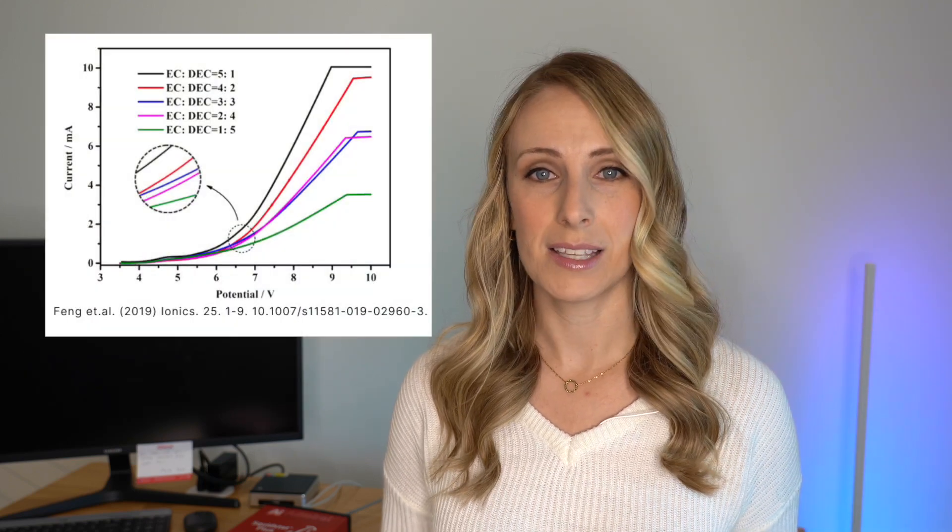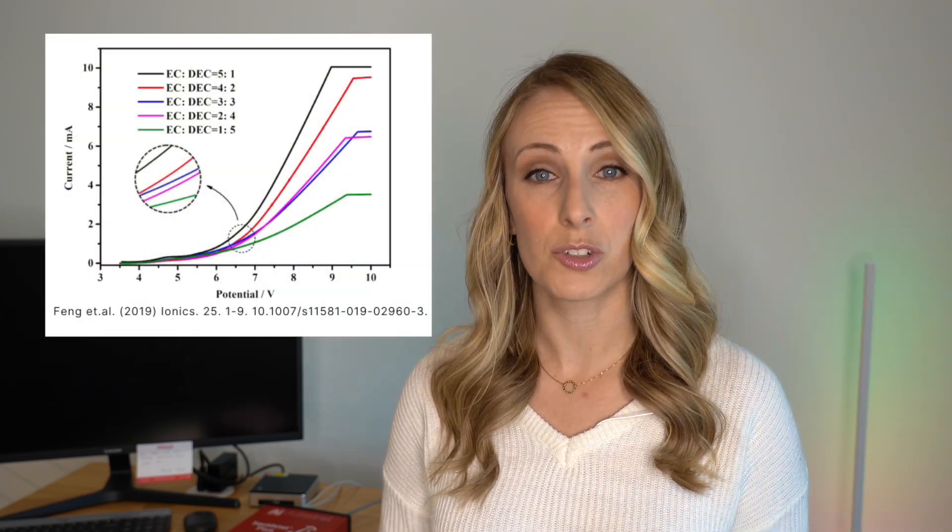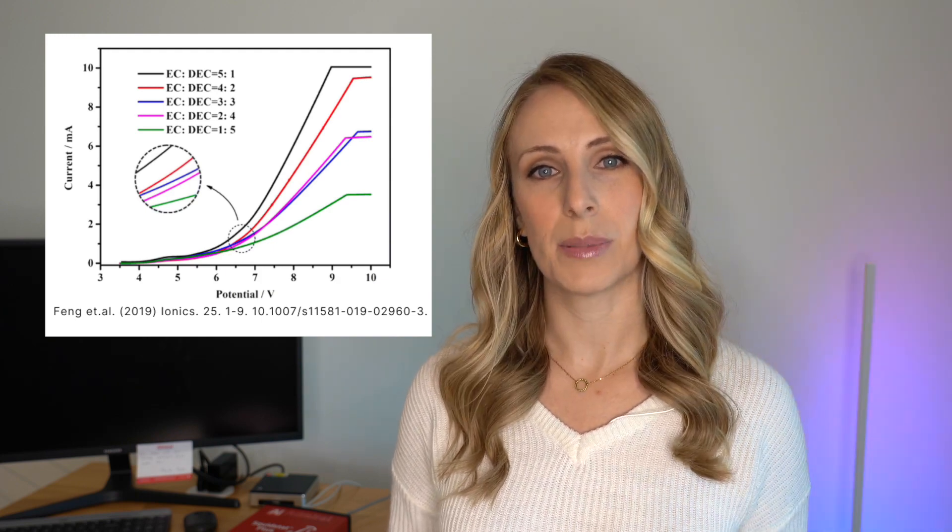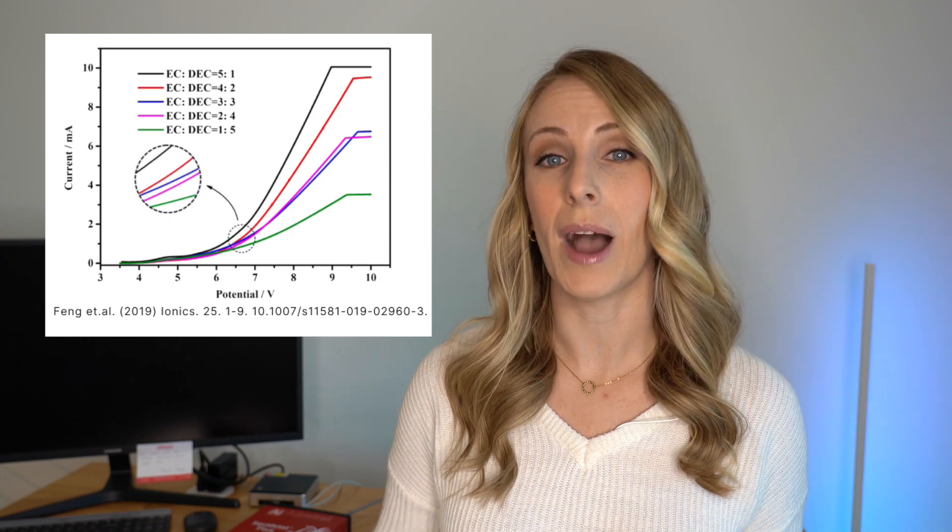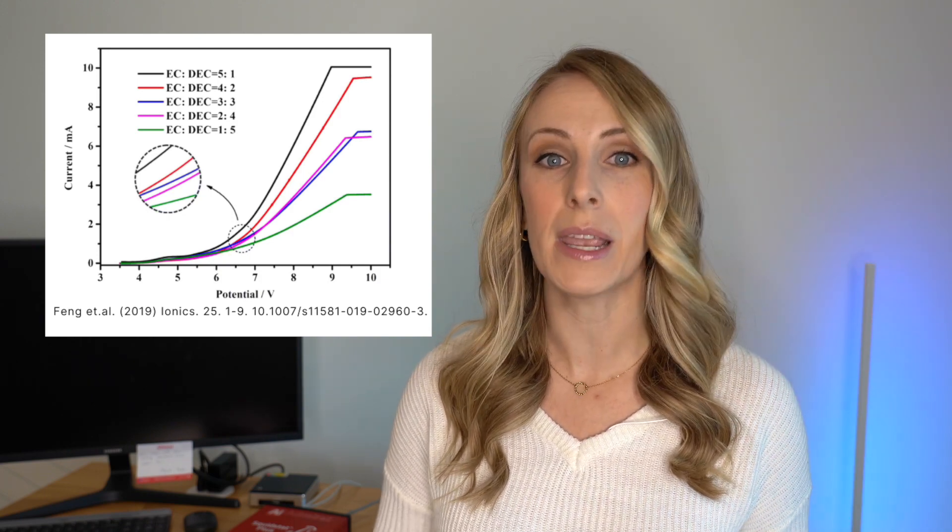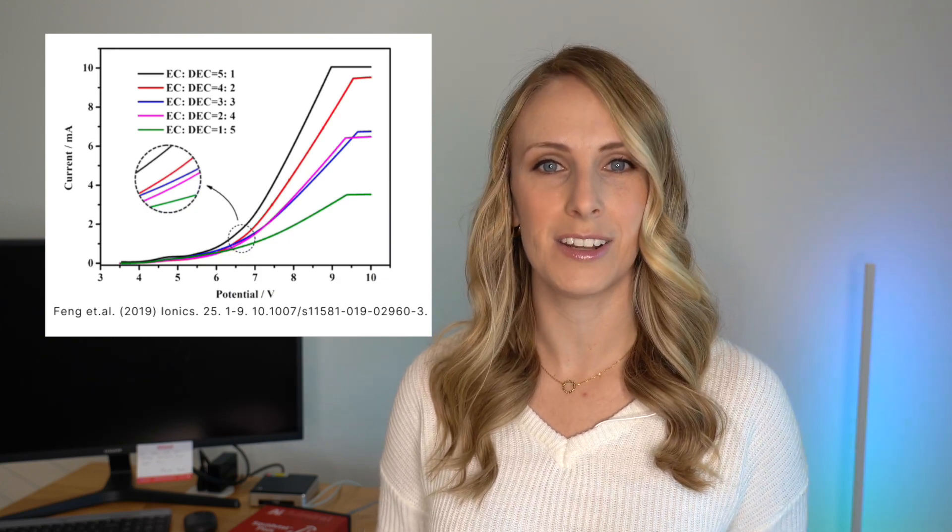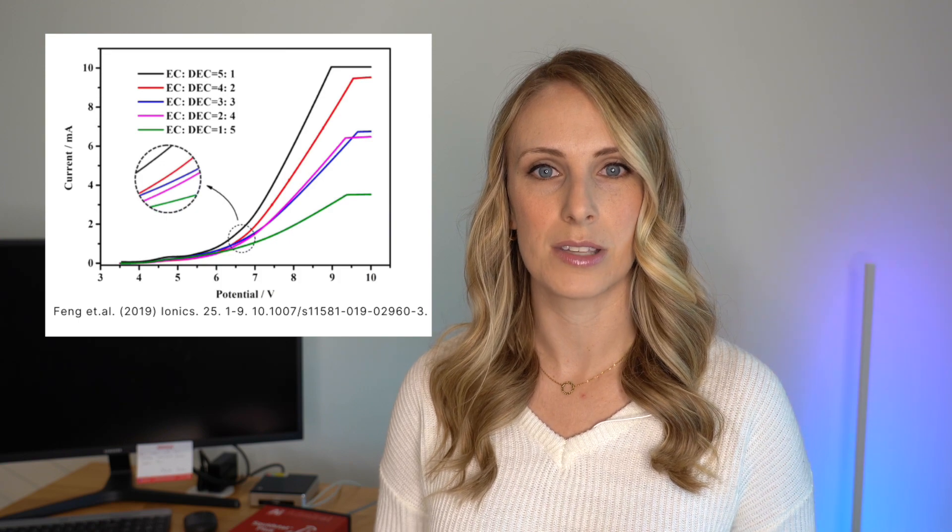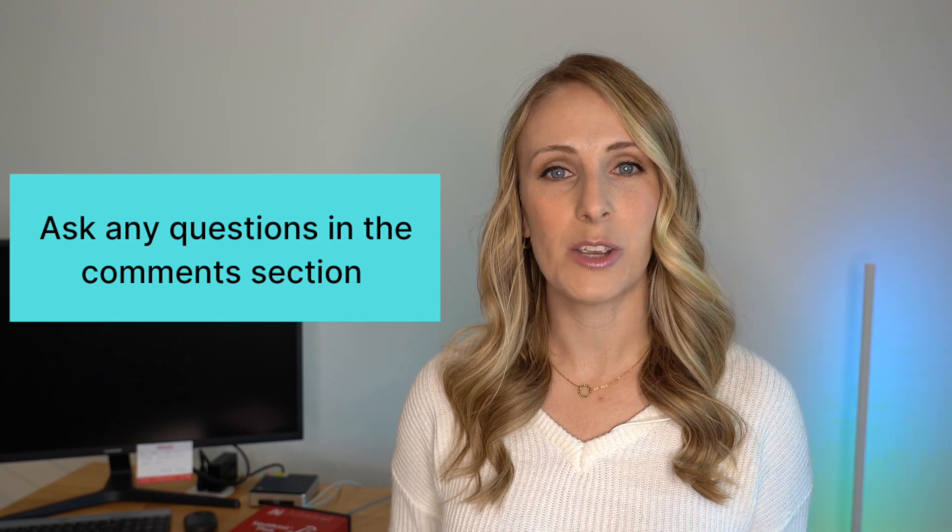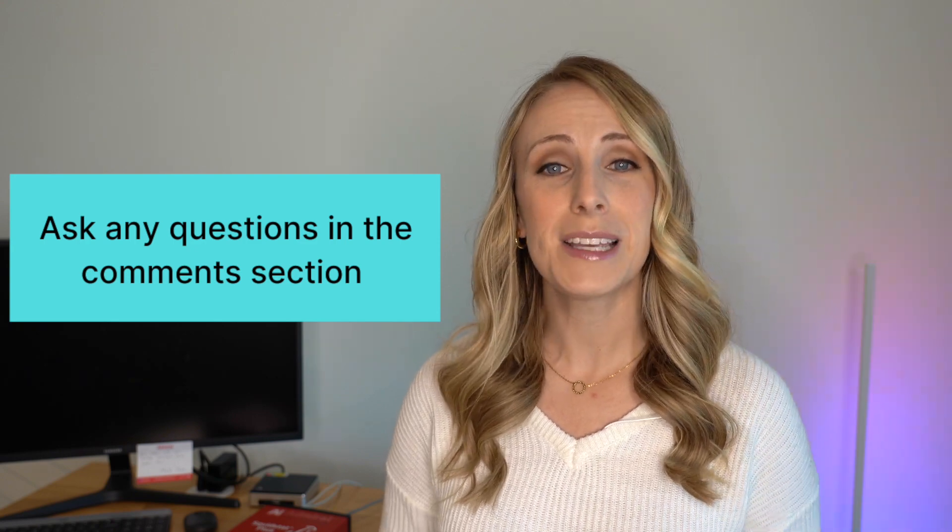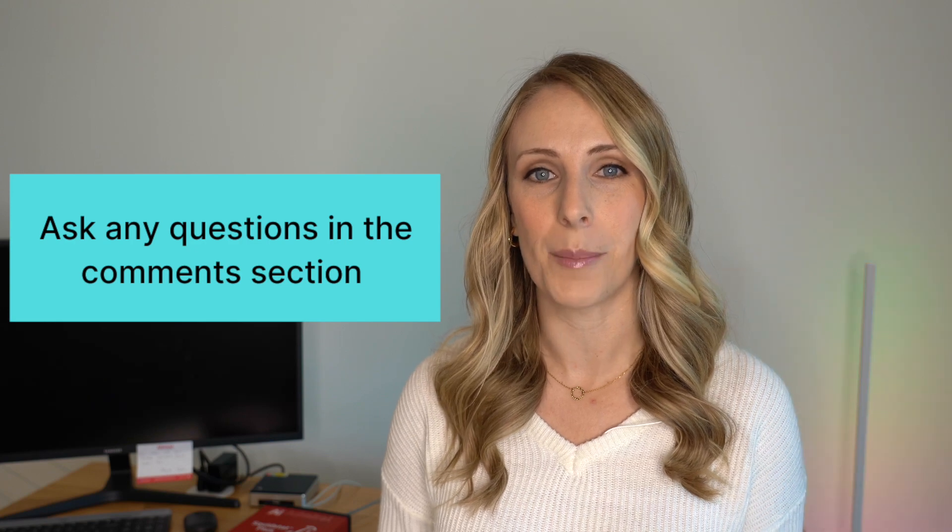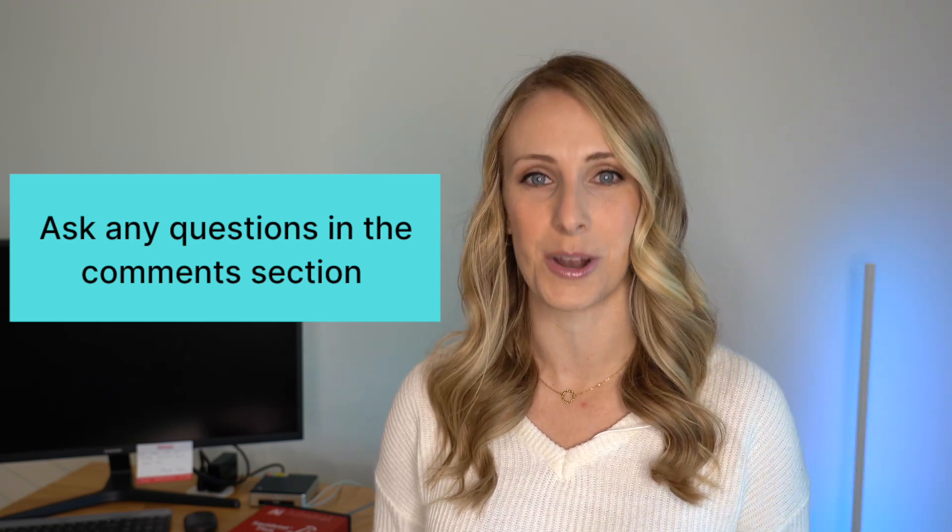I've even used LSV to measure at what potential electrolytes begin breaking down or reacting. And this was done by sweeping the potential from a low potential to a high potential, and measuring at which potential do I see a spike in current flow. That current flow, the higher current flow, indicated when my electrolyte was breaking down because it was generating a current as it reacted. If you have any questions on CV or LSV of batteries, please leave your questions in the comments below. I do want to make another video on this topic at a future time and will definitely answer your questions.